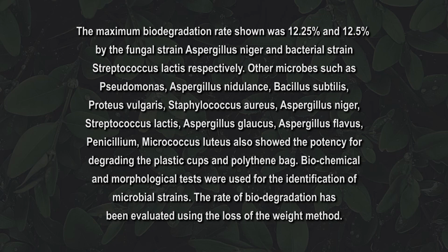The biodegradation potential of microbial isolates obtained from various soil sources such as agricultural, sludge zone, energy park, sewage water, medicinal garden, etc. were evaluated. The experimental samples used for analysis were plastic cups and polythene bags, which were incubated with fungal and bacterial strains for almost 31 days. The maximum biodegradation rate shown was 12.25% and 12.5% by the fungal strain Aspergillus niger and the bacterial strain Streptococcus lactis respectively.